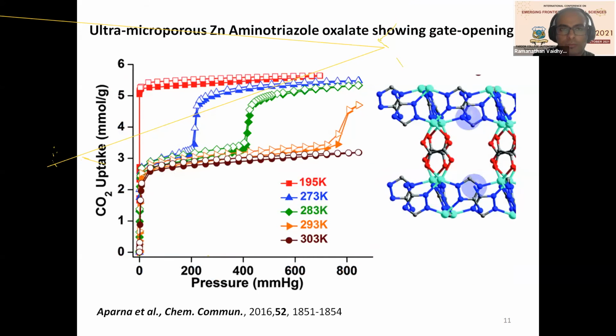Now, this is one of the works from my own group, which we did a while ago, where we show how CO2 can have a specific uptake at, say, 303 Kelvin, which is room temperature, and you do not see any change in the MOF. This is an isotherm. So I'm looking at the uptake of CO2 as a function of pressure. You can see it has a rapid uptake and then it saturates and there are no steps in this. Whereas when I go to 293 Kelvin, at around 800 millimeter of Hg pressure, you can see there is a structural opening and there is more CO2 going in.